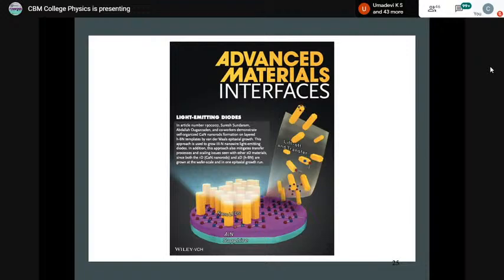So this is the graphical representation of what we have achieved. So we can have aluminum nitride, or let's say gallium nitride, on top of a sapphire substrate. We coat it with boron nitride, and then we grow gallium nitride nanostructures, and then we can peel it off just by using tape, and we can transfer it to any arbitrary platforms. This was done last year. So with this, I think I will finish.